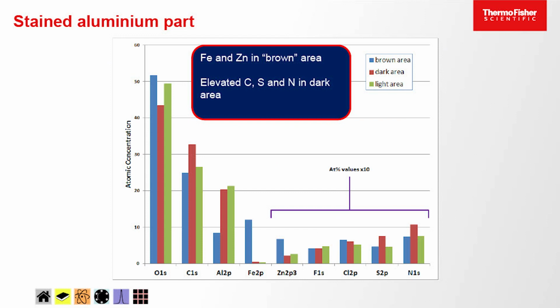And so we can now quantify all those elements and establish how much we have. And so we can see in that brown area, really, over 10% of iron presence and about 7% of zinc. But apart from that, not too much difference. But what we are seeing is lower aluminium there, obviously, with the coating of this contamination.